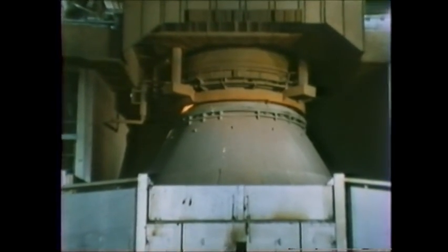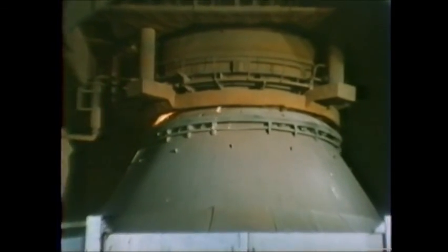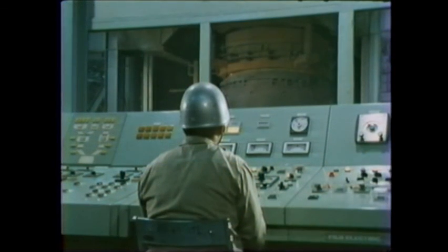Increased yield in steel making is another feature of the OG process. The closed hood process can save the iron loss due to slopping and spitting of the molten bath. This increases the tapping yield by more than 1% over a conventional open hood process.